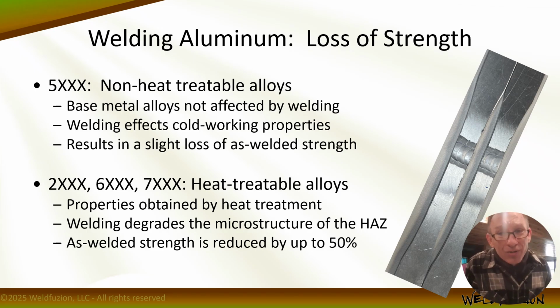So in that case, filler metal really doesn't matter as much in terms of strength compared to what the base metal is going to end up at. In that case, we would look at other properties: crack sensitivity, corrosion resistance, heat treating after welding, or anodizing after welding, right? Those are all factors that would determine what our filler metal should be in this case.